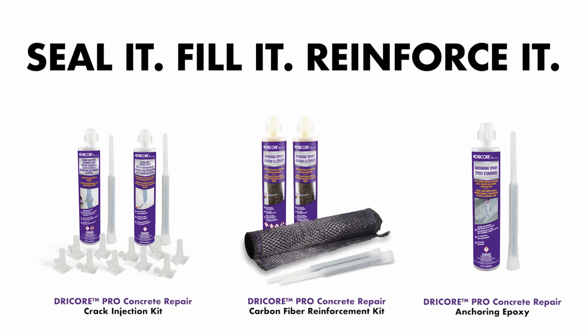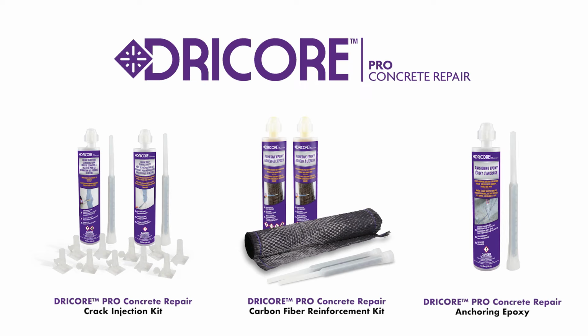If you don't want that crack to move again and crack in the future, you need to reinforce it. You drill out the crack, you seal it with epoxy, you fill it with polyurethane, and then you reinforce it with a carbon fiber mat.